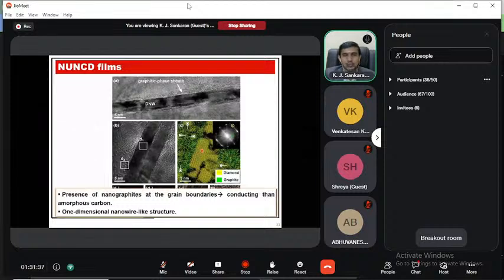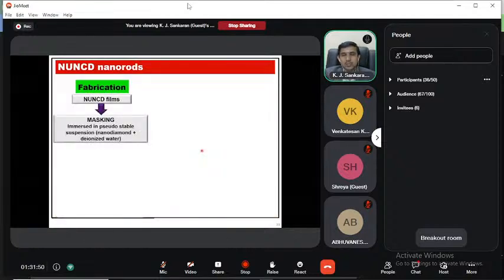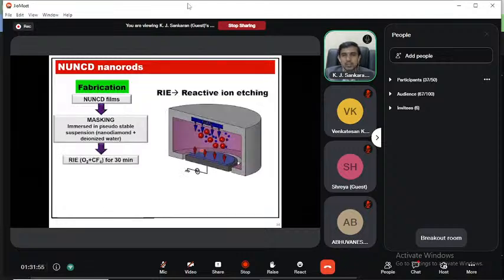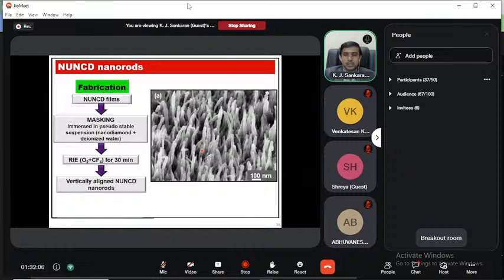So far I have shown only the film-based, flat material. But what happens when you make a nanostructure in the diamond? Diamond is a very strong material. Can we make nanostructures? Yes, it's possible. We have utilized the reactive ion etching process. We masked the NUNCD films using diamond nanoparticles of 5 to 10 nanometers. Then we used oxygen and CF4 plasma for reactive ion etching, which creates one-dimensional nanostructures of NUNCD nanorods.